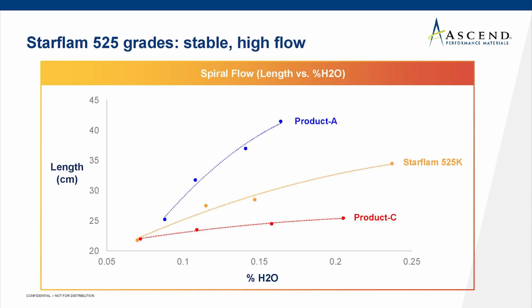Now, something important to molders is not having to shut the molding machines down when they're processing a given material. And usually they like to be able to run at least 2 weeks without having to shut down. And here we show a spiral flow length on the y-axis as a function of moisture. And looking at competitor product A, it has a very high flow, but a very steep curve response to moisture.